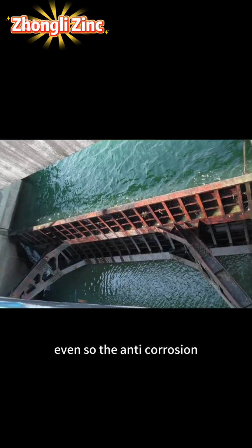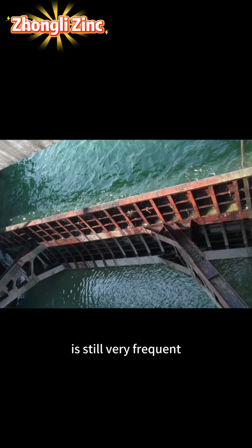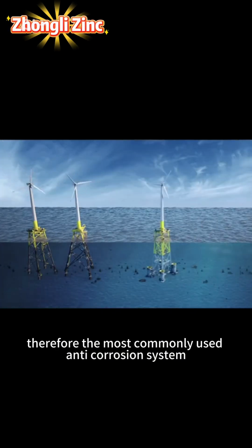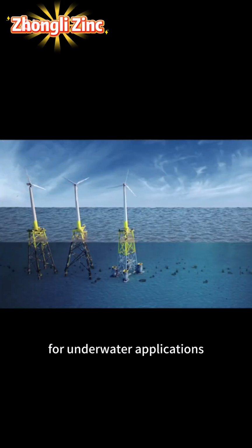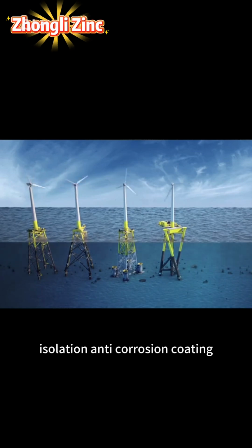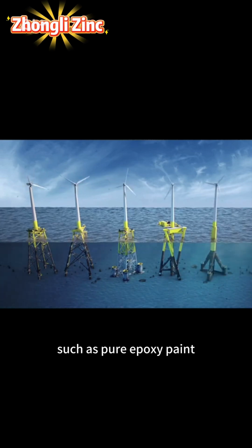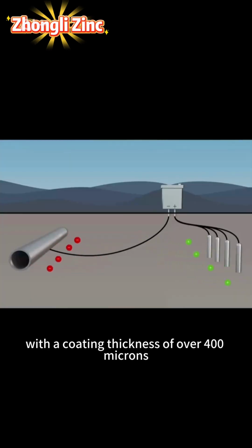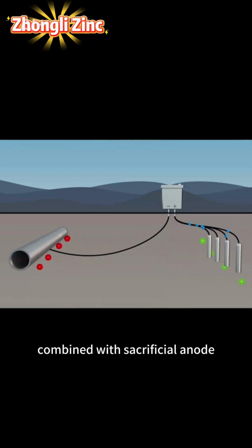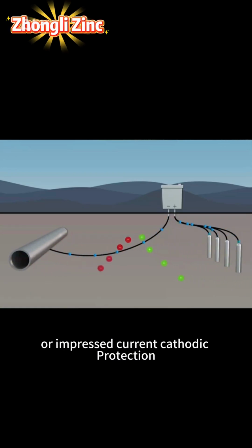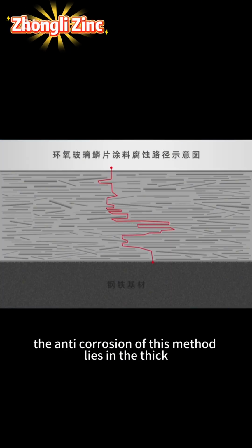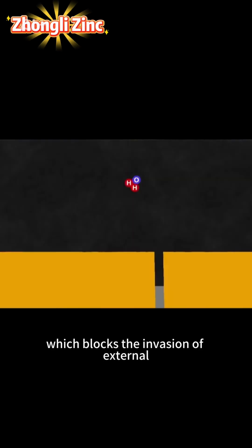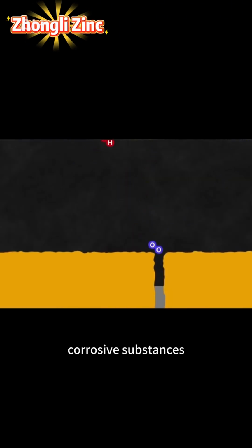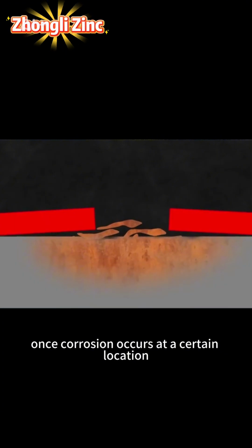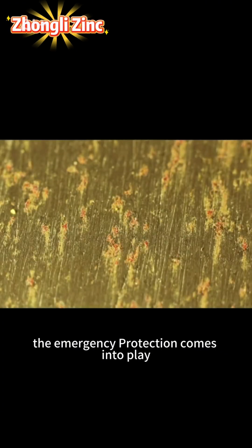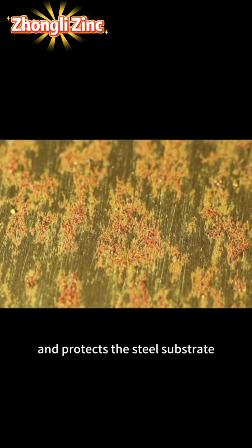Even so, the anti-corrosion maintenance of hydropower station gates is still very frequent. Therefore, the most commonly used anti-corrosion system for underwater applications is the shielding isolation anti-corrosion coating, such as pure epoxy paint, epoxy glass and flake coatings, with a coating thickness of over 400 microns, combined with sacrificial anodes or impressed current cathodic protection. The anti-corrosion of this method lies in the thick shielding isolation coating, which blocks the invasion of external corrosive substances. Once corrosion occurs at a certain location, the emergency protection comes into play. It inhibits the spread of corrosion and protects the steel substrate.